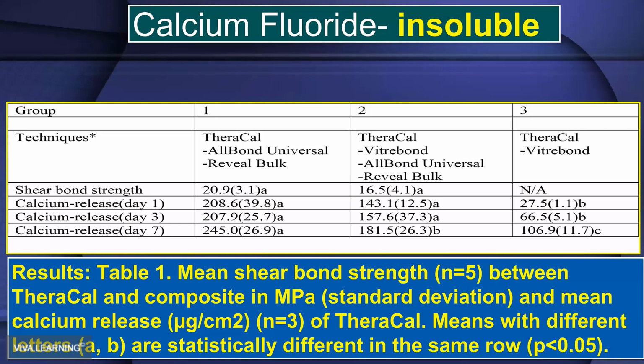208.6 micrograms per square centimeter. But if you just put in the Vitrebond, it drops down to 143. And you see it really drops down when you just have TheraCal and Vitrebond. It is incredible, the drop in strength and the drop in calcium. So what happens is, of course, the calcium combines with the fluoride to make something that's insoluble. So you can't measure either the fluoride or the calcium.